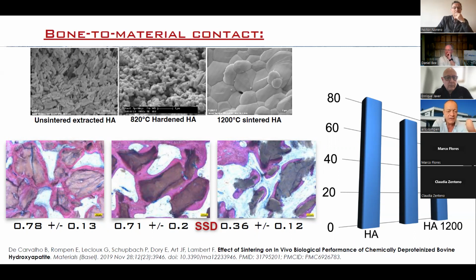Completely the same level of bone to material contact with the hardened material, which is still very rough. It's a modified surface roughness, but it's still very rough. And when we sinter the material at 1200 degrees, that's exactly the same material, but just melted, sintered, then we really kill and divide by 2 the bone to material contact.